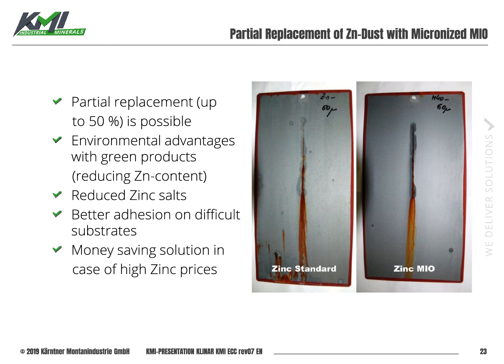When you look at the test panels on the right hand side, these are test panels of one of our Italian-based customers doing an aerosol spray can zinc-rich coating. The left panel shows his standard formulation with a zinc loading level of roughly 60%. On the right hand side, it's the new formulation with zinc MIO, where he replaced 50% of the zinc with the micaceous iron oxide grade Miox Micro 40. And you can see there is no difference in the performance after doing a salt spray test.